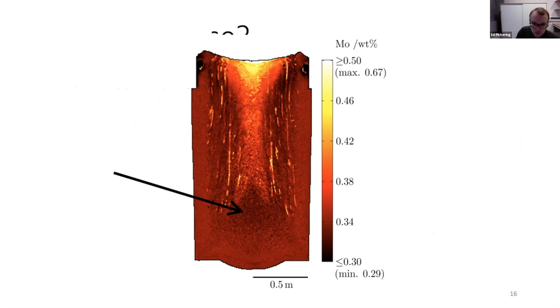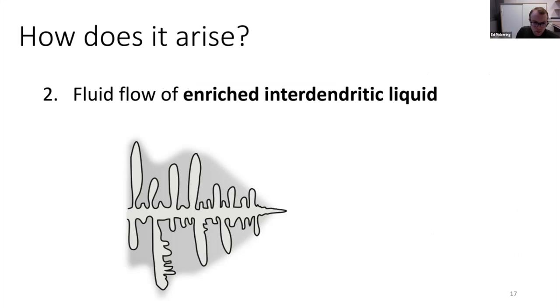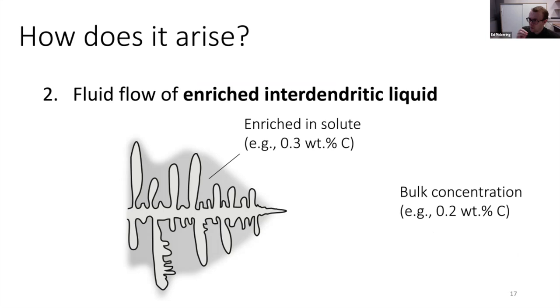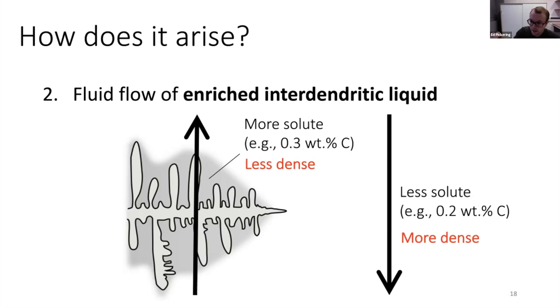Second mechanism, fluid flow of interdendritic liquid. If we have a dendrite surrounded by enriched liquid, let's look ahead of that into the bulk liquid. If the bulk liquid has the bulk concentration of the alloy, let's assume that's 0.2 weight percent carbon, the enriched liquid will be enriched in carbon and elements like silicon and other elements. Let's take an example where we've got 0.3% carbon. This basically means that the enriched liquid is less dense than the bulk liquid. And this means we have a convective flow set up, a buoyancy-driven flow that will arise, and that looks like this. So the interdendritic liquid rises and the bulk liquid sinks relative to each other.